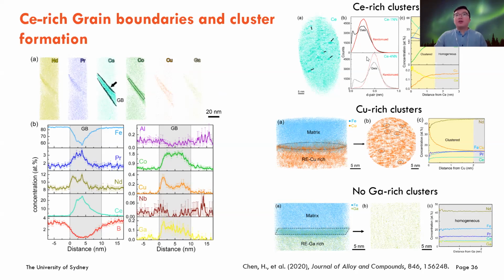The other merit of the atom probe is the cluster analysis. We do three types of analysis in this sample. We first see the cerium-rich clusters at the grain boundary phase. And we can also see some copper-rich clusters at the interface between the matrix and one type of rare earth-rich phase. But there are no gallium-rich clusters here.